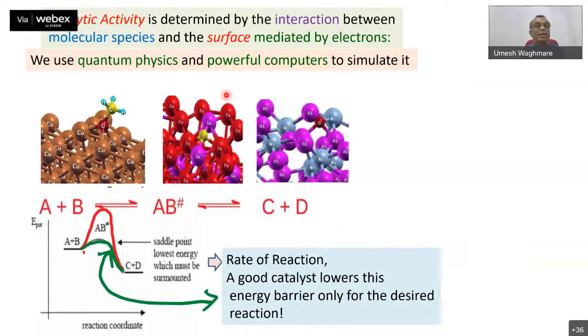Now, the second part is the catalytic activity for CO2 reduction, and catalytic activity is determined by the interaction between molecular species and the surface of the catalyst, mediated by electrons. So this is where we use quantum physics and powerful computers to simulate it. The basic idea is you want to start with a reactant and arrive at product AB. To do that, there is usually an energy barrier to cross, and that energy barrier decides the rate of reaction. Whereas if one does that reaction on a catalytic surface, this barrier is reduced. That's how the catalyst works. It doesn't really change itself in the reaction process, but it facilitates a chemical reaction.